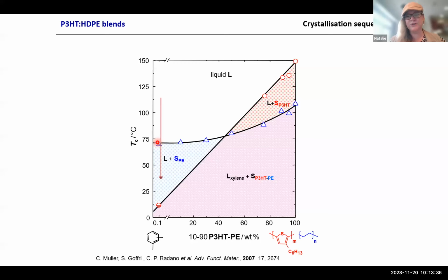Why is this important? If you just go and spin coat, which I anyway hate, I must say, you first have crystallization of polyethylene, and then the P3HT is supposed to crystallize in this sea of solid polyethylene. As you can imagine, this will not work, and you will not get good films, and definitely not good films of good electronic and mechanical properties. So what this phase diagram tells you is you should cast the solution at higher temperature so that the P3HT crystallizes first at this dot, and only afterwards the polyethylene.